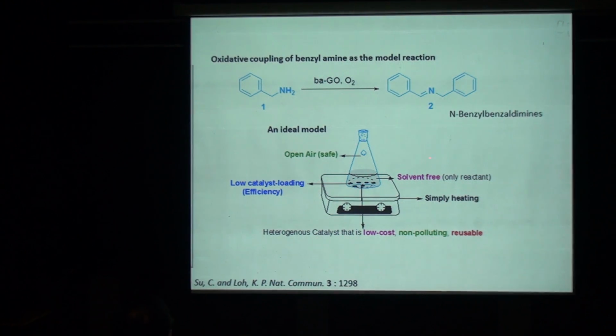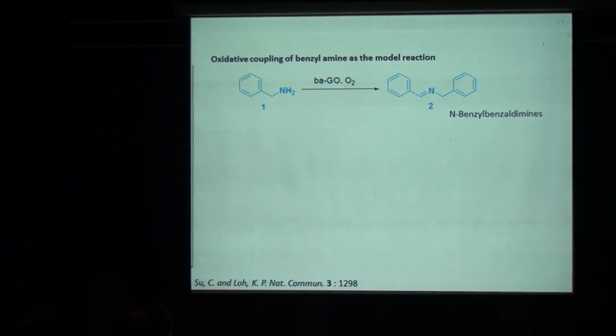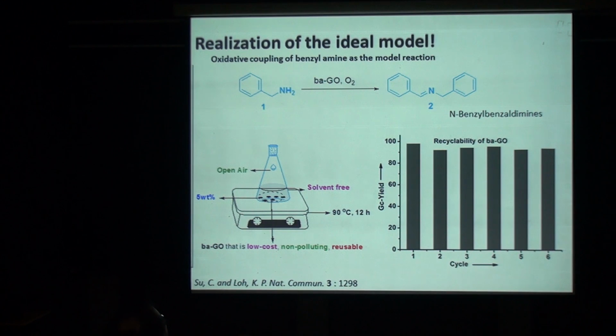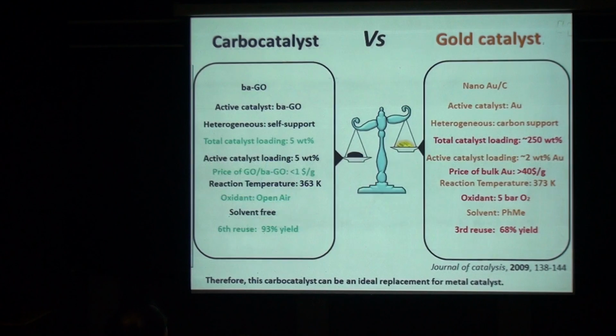We can achieve very high catalytic efficiency, about 90% yield of the product with very good recyclability. So this BAGO is a low-cost, non-polluting, and reusable catalyst compared to gold on carbon. Now, normally, for the same reaction, you carry out using gold on carbon.